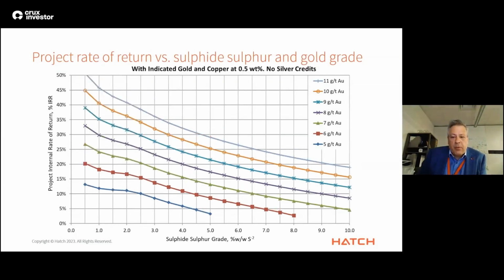For copper at 0.5% by weight, the IRR decreases for all gold grades due to the additional capital cost of copper recovery using an SX-EW circuit. The model shows that at 0.5% weight copper, recovery of copper is not economically beneficial to the project, other than it reduces the consumption of limestone needed for solution neutralization.